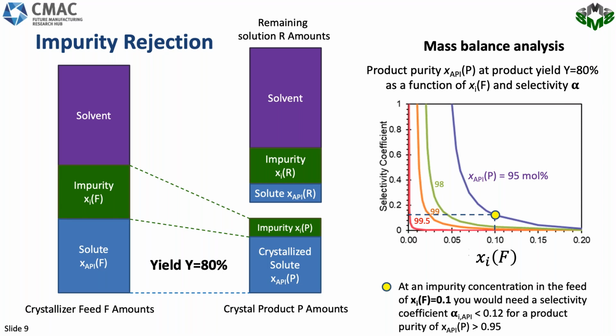So that is giving you, say, a mathematical framework to look at, if you set a certain yield and you want to reach a certain impurity level in your product, how much should the selectivity then be in order to reach that? And then you compare that to measurements, and then you can see whether these two are smaller or larger than each other. If your target selectivity is much smaller than your actual selectivity, you have to do some impurity rejection improvements. If your target selectivity is much larger than your actual selectivity, then impurity rejection is not a problem.